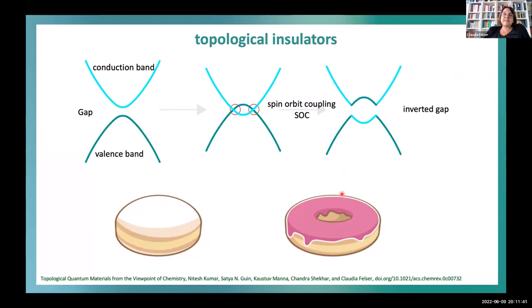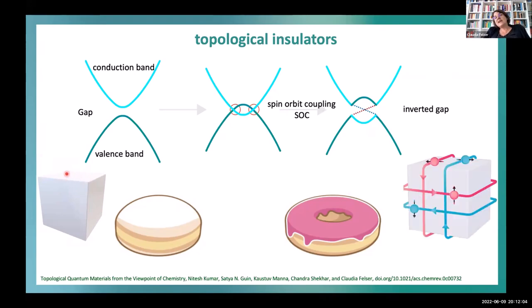So this has a consequence, because here we suddenly have topologically protected surface states, which are also spin polarized, and this we like in spintronics, you know. And so if you think about our crystals, in our simple material we have, for example, an insulating crystal. So we have no states in the crystal and no states on the surface. But if we have this topological crystal, we have some surface states where the spin and the momentum are locked. And this is very special, if the spin and momentum are locked.